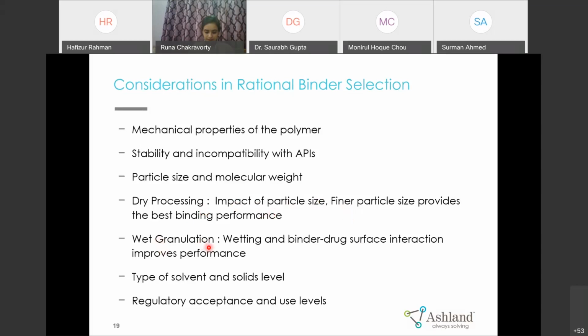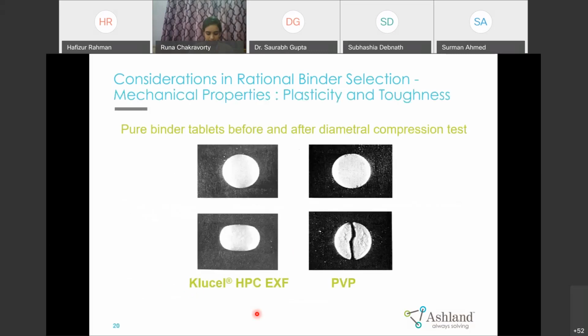If you are doing wet granulation, then binder drug surface interaction is very critical, so API hydrophilicity or API log P is very important to select the binder. Then the type of solvent and the solid level of the binder, whether you are dissolving it in water or an organic solvent. Then regulatory acceptance and use level, that is, how much concentration you have to use.